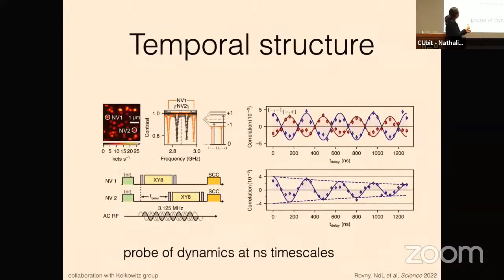Okay, the last trick that we can pull is that now let's take two NV centers that have different orientations with respect to the magnetic field so that they have different spin resonance frequencies. Now we can have independent control over the two NV centers and then use that to set a time delay between the two NV centers. So now I start the clock on NV1, wait some time, and then start the clock on NV2. And in doing this, now if I have this kind of signal where shot to shot it's phase random, if I just plot this correlation as a function of time delay, I can still reconstruct that the signal is coherent within this time window. Okay, so even though this is averaged over something like an hour or a few hours of averaging, and the phase is totally random across shots, because it's sort of like a pump probe measurement, I can basically reconstruct the coherence on short timescales.